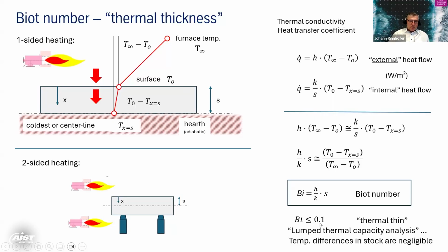It can be thick when Biot is more than 0.1. So this 0.1 barrier is a little bit arbitrary, but this is how it is usually used in the literature and in practice as well. So we can say something is thin if you can neglect the temperature differences in the stock. So if there's not a lot of difference between the surface and the core, or the surface and the colder end of the slab. So that is the so-called lumped thermal capacity analysis.